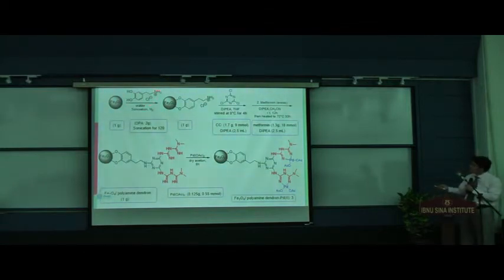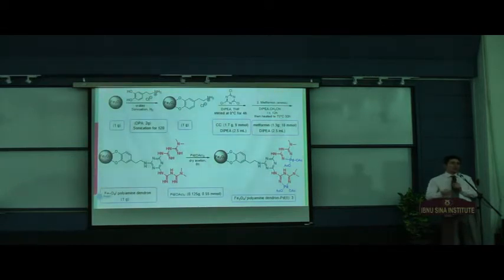If you take dopamine, you can easily stabilize these nanoparticles and keep them stable in solution. So we made this, and with the help of this spacer, again we put metformin in excess amount at the surface. If you look here, the loading percentage of metformin is too much. We can call it a polydentate or polydendron-like modified core-shell system. And also, of course, complexation of this metformin with palladium was studied, and we used all of these in simple organic reactions as recoverable catalysts.